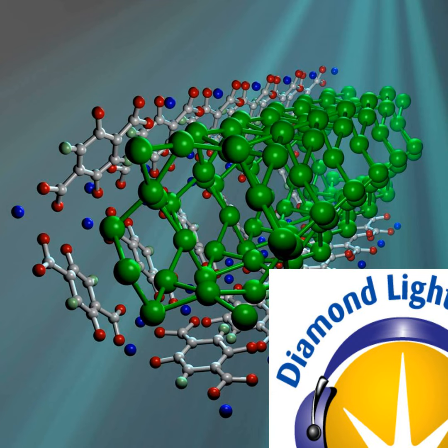And so what have you managed to see with your catalyst to date? Has it been quite effective, and have you managed to see good yields of methanol being produced? Initially, the selectivity, that means it's going towards the methanol, is pretty low. It's roughly about 15 to 20%.